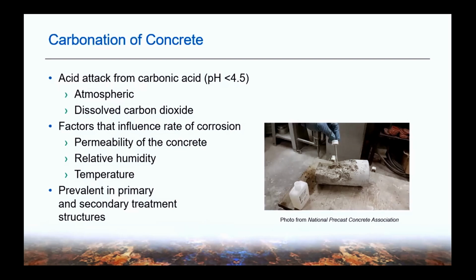So, the permeability of the concrete, higher temperatures, even higher relative humidity numbers there can speed this up. But I've seen this really scattered throughout a treatment plant, but probably the areas that are the most prevalent are going to be in your primary and your secondary treatment structures, with aeration basins really being one of those where I see this fairly frequently.